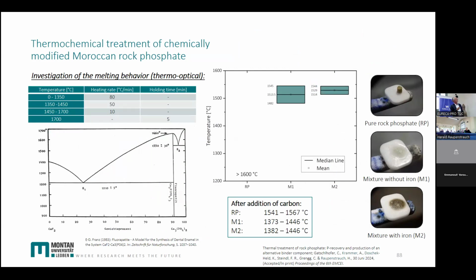Here another word, which I didn't mention earlier, what is really important is, of course, the melting behavior, especially in this type of reactor. We see we have rock phosphate, pure rock phosphate in this example, mixture without iron and mixture with iron. And you see the behavior is completely different. In the first case, the first picture at the top, we have quite high temperatures, and it didn't change a lot. At much lower temperatures, the mixture 1 melts at comparably low temperatures compared to the first case, and similar in the mixture with iron, but it looks different. So this melting behavior, the viscosity is different, and this may affect the chemical reactions taking place in the reactor.